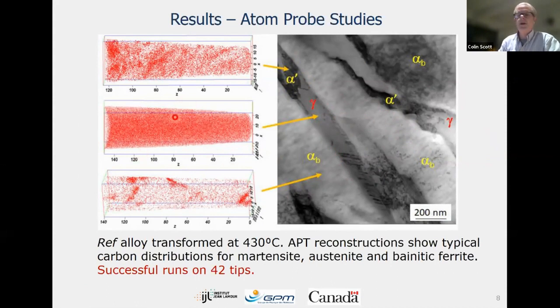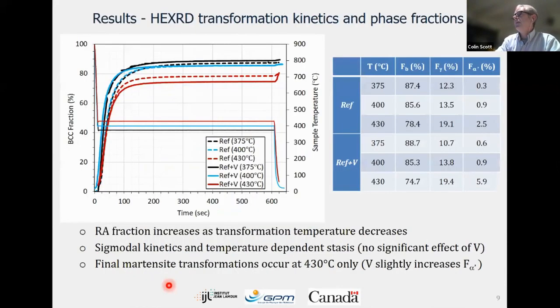So the austenite carbon is uniform. In the martensite, carbon is not uniform, but is very, very dense. And in the bainitic ferrite, you can see regions where you've got strong clusters of carbon, but there's also regions where there is uniform carbon, apparently. Right, so I'll move on from that.